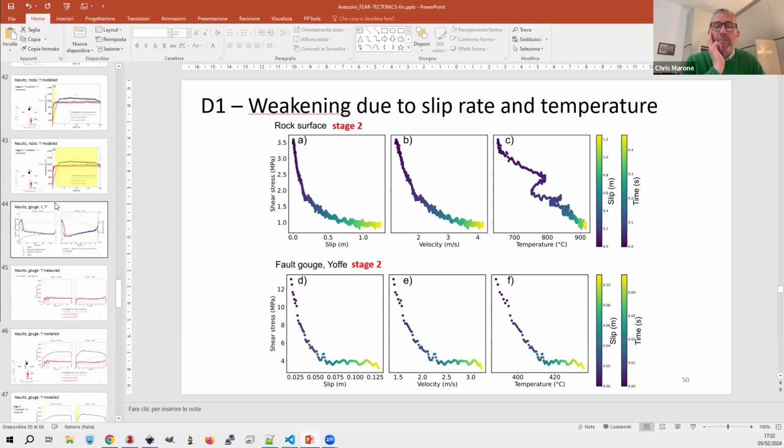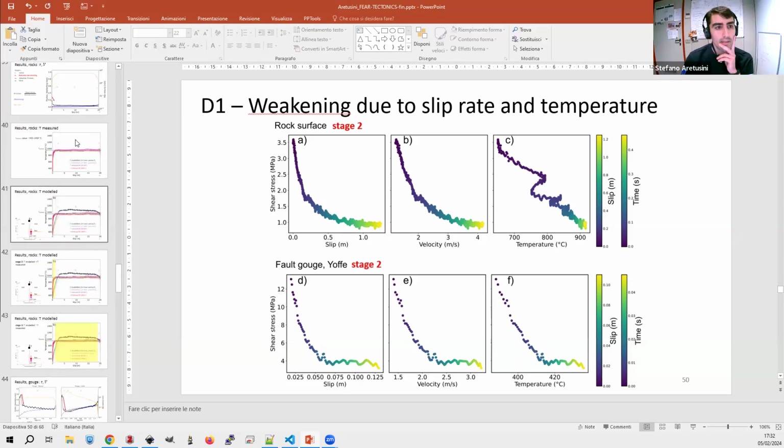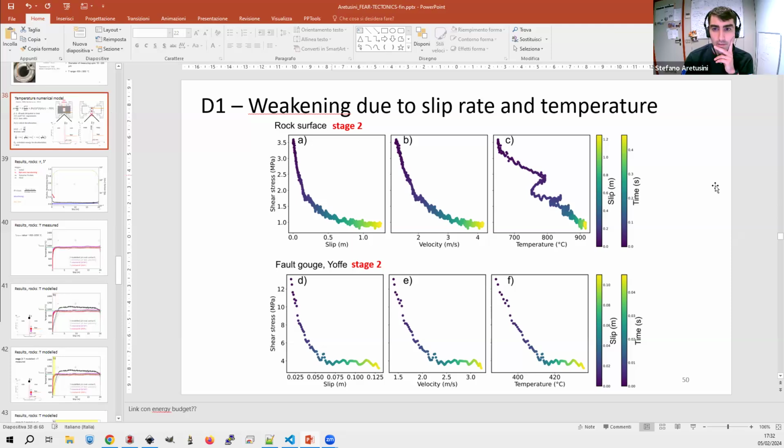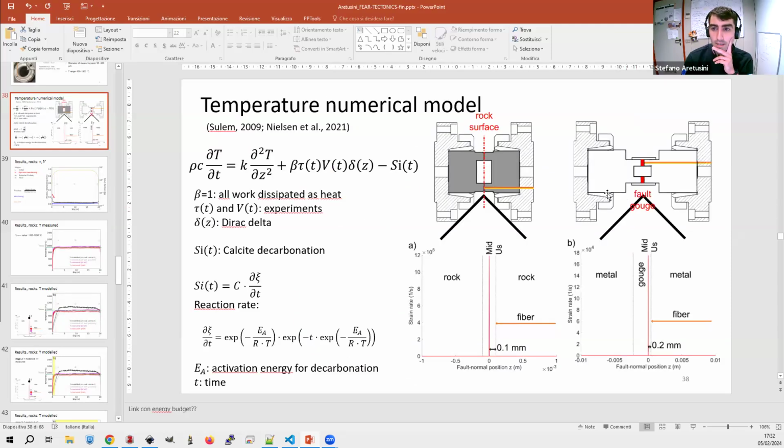Right. Yeah, based on that paper, we decided to develop this sample holder in a titanium alloy. Actually, Chris Marone did it, in fact, and we tested it later in our lab. So the idea was to use a metal with a sufficiently low thermal conductivity, diffusivity actually, as similar as we could to natural rocks, which are very insulating in terms of temperature.